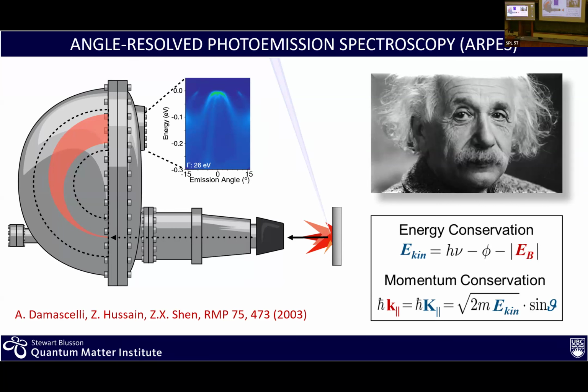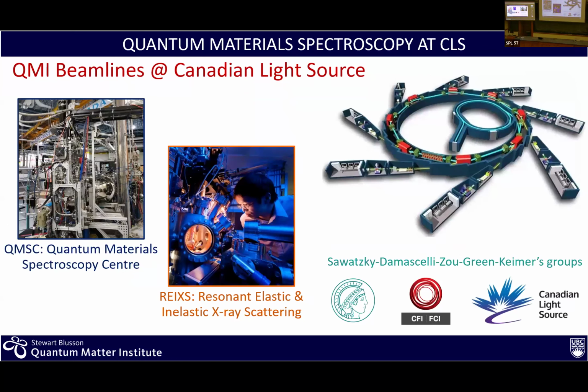And using simple conservation laws, knowing the photon energy and the work function, you can now extract the binding energy in a solid and the crystal momentum, so the momentum of the electron inside. In practice, an image like this can be directly compared to calculations of electronic structure you would do by density functional theory. And as we went in and did these experiments, the first step is, of course, the instrumentation.